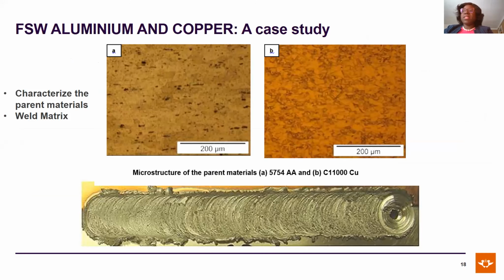So it is also expected that for a start, before a researcher even goes into conducting the welds, the researcher should first of all characterize the parent materials, because you need something to benchmark. So when we produce the welds, we then have something to benchmark to, the parent materials. So we characterize the parent materials individually. It is also expected that we join, first of all, the parent materials as similar materials. For example, when I want to join aluminum to copper, it is expected of me as a researcher to start by joining aluminum to aluminum of that particular grade that I want to join, to also join copper to copper, and then progress to come up with my weld matrices.